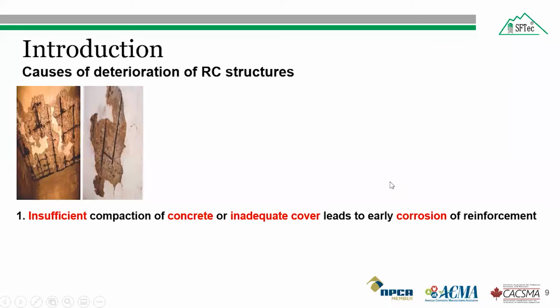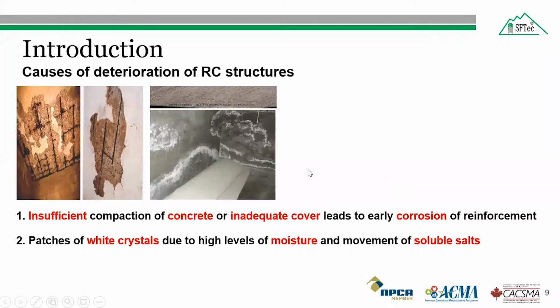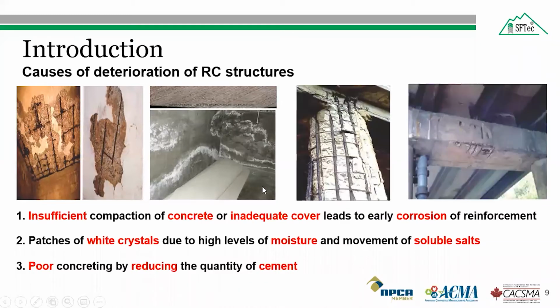Now coming back to our main presentation, the substandard workmanship in reinforced concrete structures due to insufficient compaction of concrete or inadequate cover to the reinforcement causes corrosion of the steel bars, and a high level of moisture and excessive fluctuations in heating and cooling can promote the movement of soluble salt, which leads to patches of white crystal as shown in this figure, and can cause considerable damage to the concrete structure. And if the minimum quantity of cement is not provided, it will lead to poor workability and lower the strength of the concrete. Therefore, it will require external strengthening.